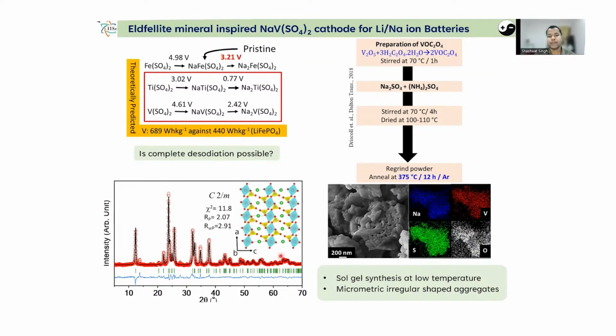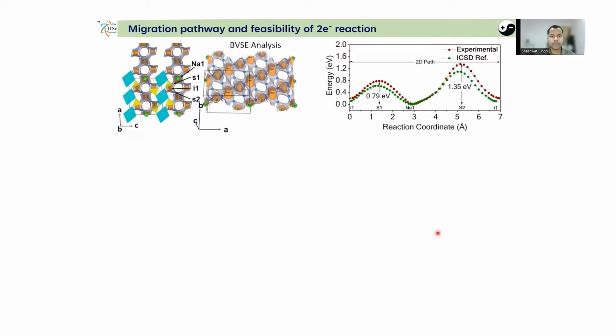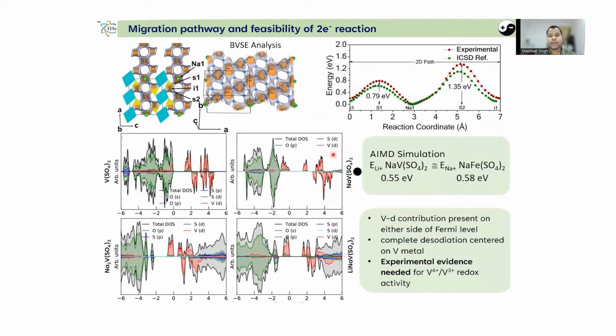and checked its phase purity with Rietveld analysis, and we see that this is a layered structure where the lithium or sodium sits in between the layers, and the incoming guest ion can sit in these positions. From BVSE analysis, we clearly see that the incoming lithium or sodium ion will be sandwiched between the host sodium as shown here, and overall the material would offer a 2D pathway for sodium or lithium ion migration. Further, from the DFT based calculation, we proved that all along the reaction, that is the two electron reaction, vanadium would be the redox center, as seen here in the increased contribution of vanadium 3d orbitals near the Fermi energy level. However, experimental evidence of the second electron reaction is still lacking.